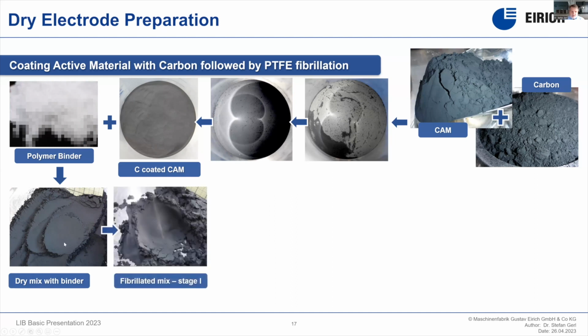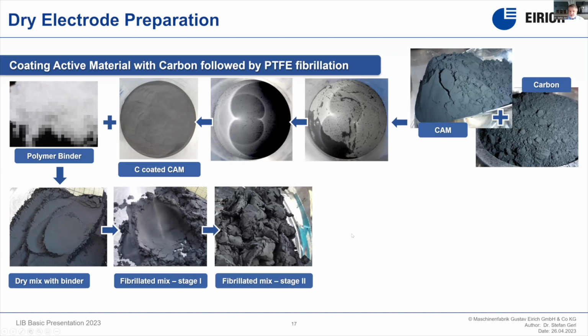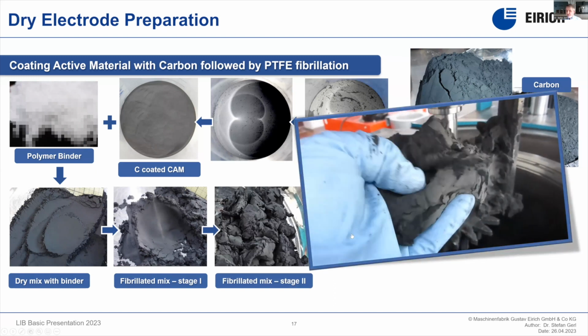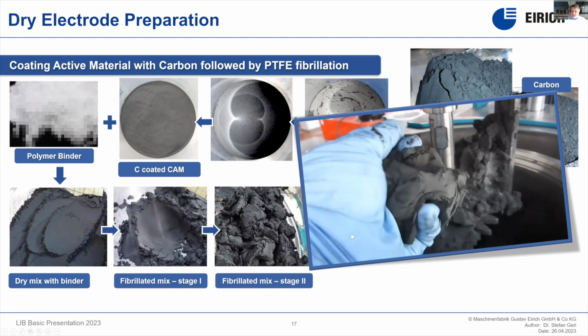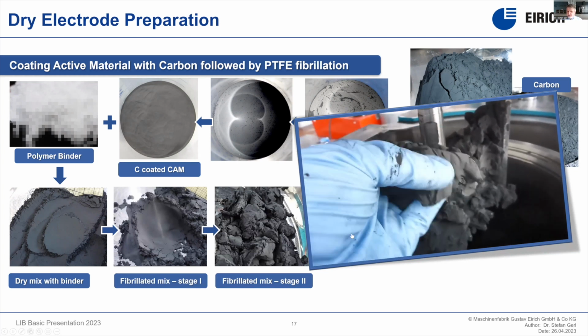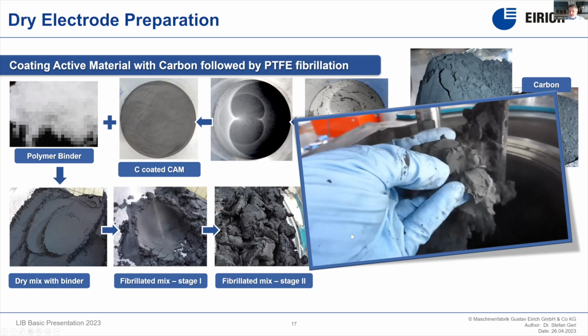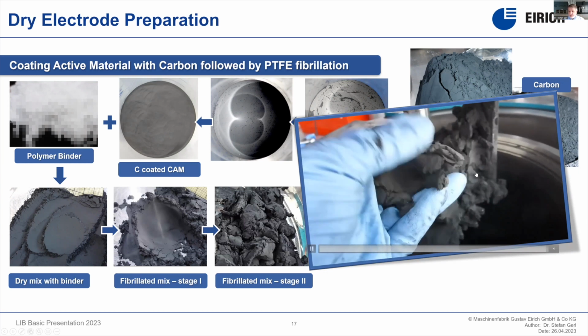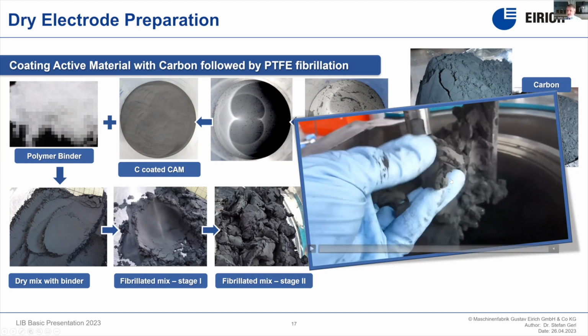Or we are now starting fibrillating the material by introducing higher shear forces and heating up the mix. And then we see after a certain period of time or certain temperature that we can form the material if we are pressing it. And depending on the kind of PTFE and the shear rate and the time, we have really a full plastic body which can be formed. And you could easily imagine that this material can be rolled out like a cake to form a freestanding film. The problem for this material is, of course, that the handling is quite complicated, the dosing is quite complicated.